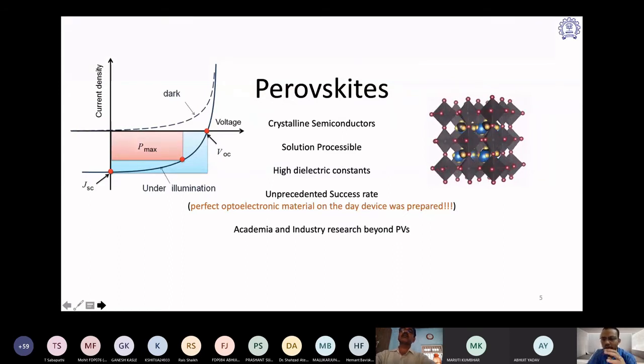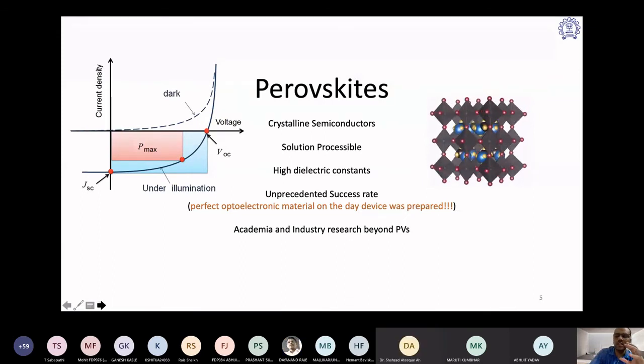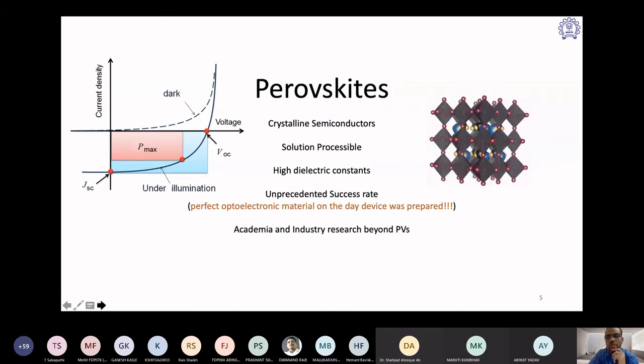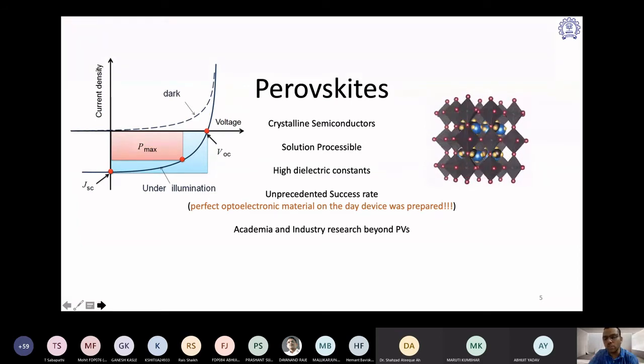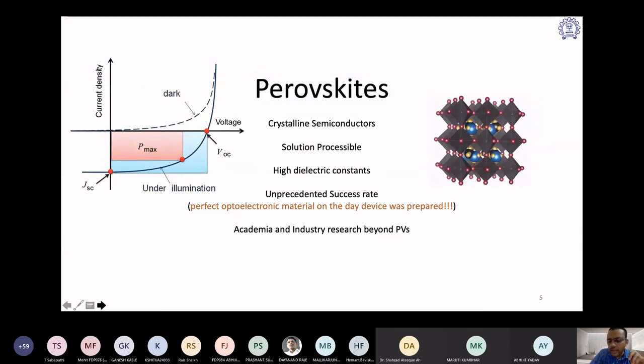So while keeping the crystallinity intact, but changing the crystal structure in the presence of light, that becomes very interesting. Moreover, when I say these materials are being used in solar cells, that immediately tells you the band gaps are in the range of 1 to 2 electron volts, and that kind of band gap material, with crystalline nature and solution processable. So the crystallinity and solution processability, both of them are rare things.